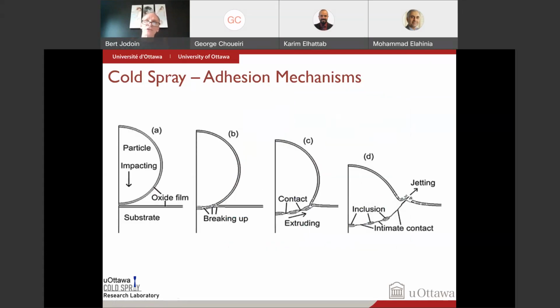So in cold spray, we get that too. We get our particle that we accelerate and the substrate. Both of them have a native oxide layer. That's why we need to throw this tiny ball fast enough so that you're going to have enough deformation at the interface to break this oxide, so that you get this extrusion of material here where you're going to get this intimate contact and then the bonding. So that's metallurgical bonding, and that's why we need to throw the particles fast enough. Otherwise, you don't break the oxide and you cannot get a clean metal-on-metal surface. So that's the metallurgical bonding mechanism that you get in cold spray.